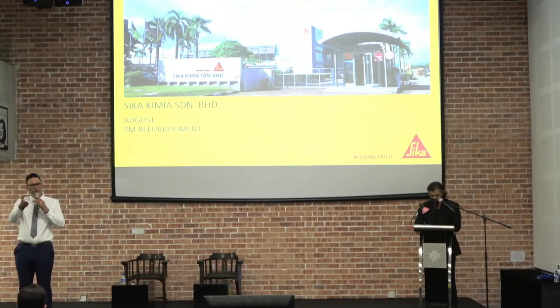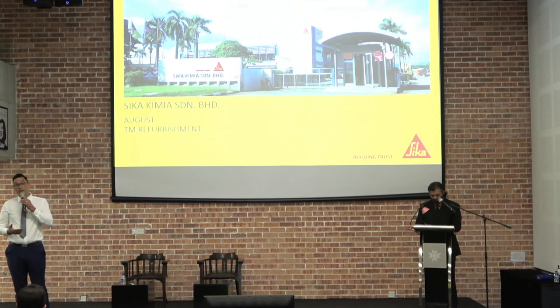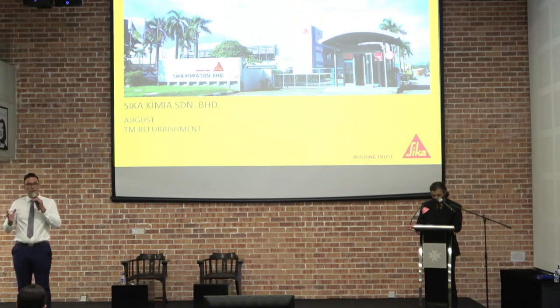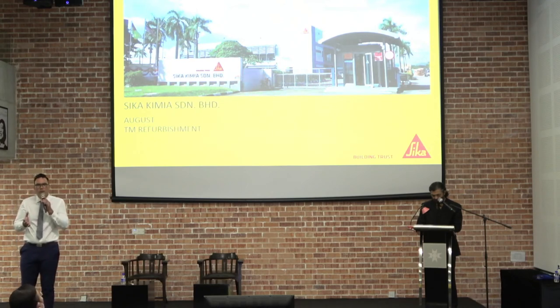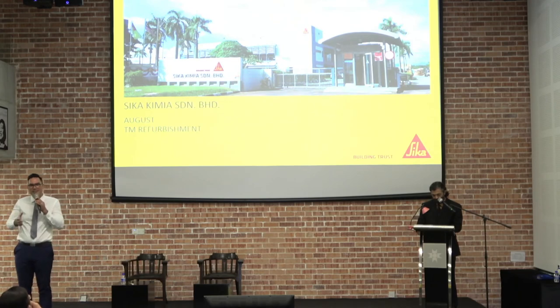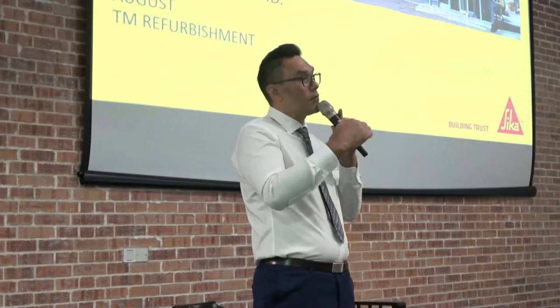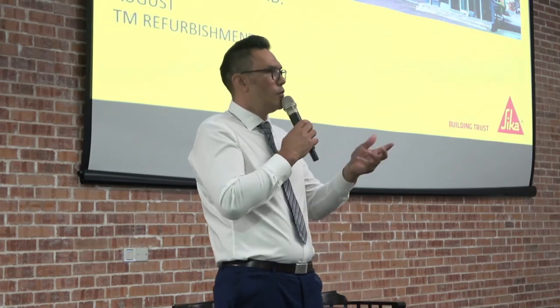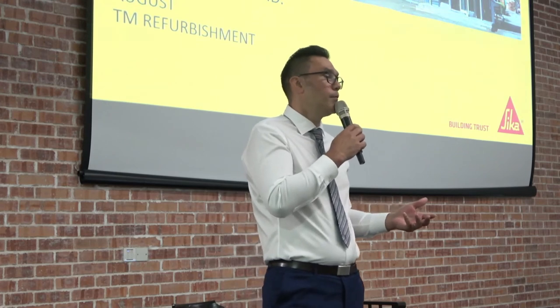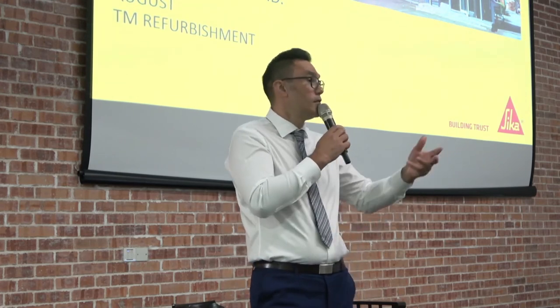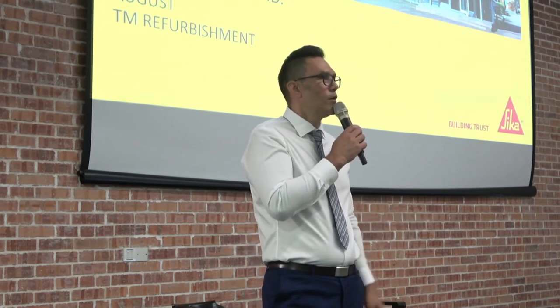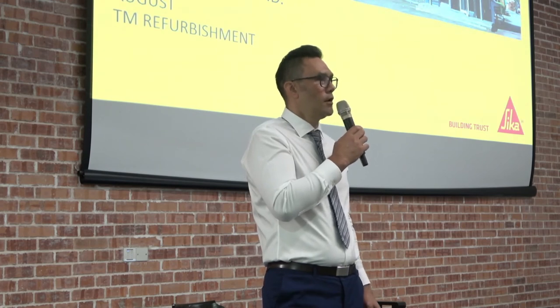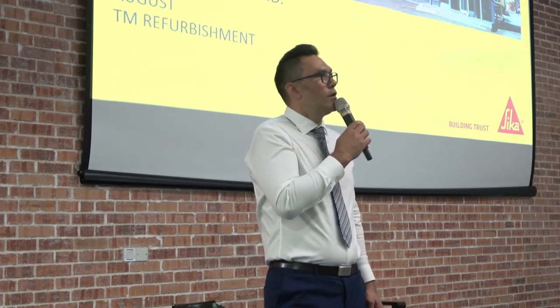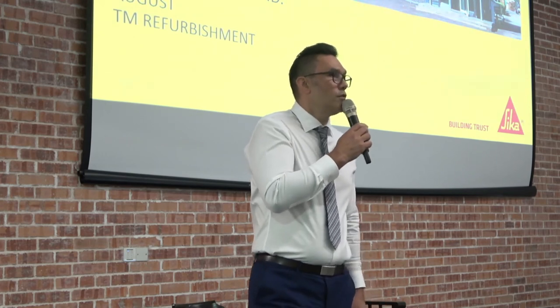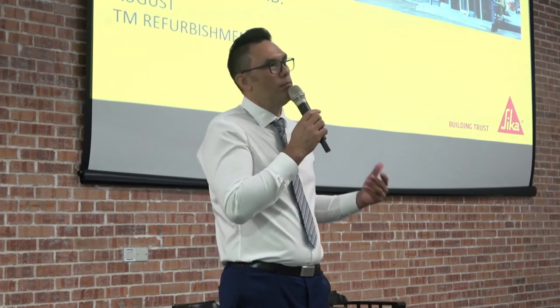Okay, so very short answer, yes. So the Sarnafil that Mr. Lau, I think, was talking about earlier on is already tested for 30 years with root resistance. So inside a test block, according to a standard, they grow a tree, and then they come back and check it in 10 years, and they come back and check it in 20 years, and no penetration. So the roots from a tree can't penetrate, so that has root resistance. There's also the same testing for liquid applied membrane as well. So there is an actual test method for it. So yes, the PVC membrane is root resistant, as is the liquid applied systems that Sika have as well. If you don't have the root resistance, you're right, they will find a way through, especially if you use, say, a traditional bitumen-based material.